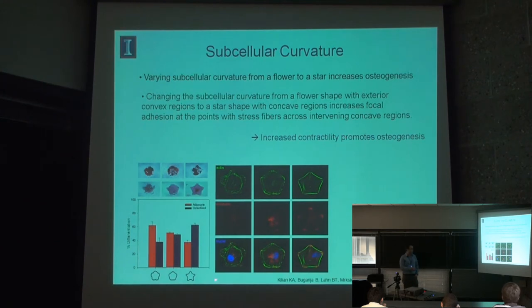And the reason is that there are these non-adhesive spaces between these points where the cell has to overlap. And this is a cue to generate a lot of stress in the cells. And so they develop these strong stress fibers that are then anchored by very large focal adhesions, sometimes on the order of tens of microns, right on the tips of the cell.